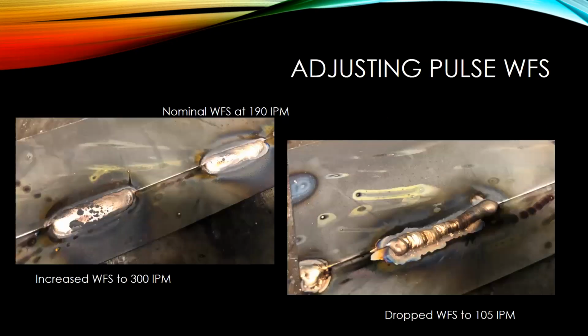So here's a couple welds I took. Basically I just dialed in the arc using pulse. This was my nominal wire feed speed at 190 inches per minute. It was just a parameter I dialed in and did a weld with, and then I wanted to show what the difference was if I really increased that wire feed speed or if I dropped it down. As you see, as I took that up to 300, it really added a lot more heat into that. You can see that it drew more steel into the weld puddle. And then as I really dropped that down, I really took a lot of heat out of the arc, and you can see that it got really ropey on top of that plate and didn't wash out at the toes like we would want it to.